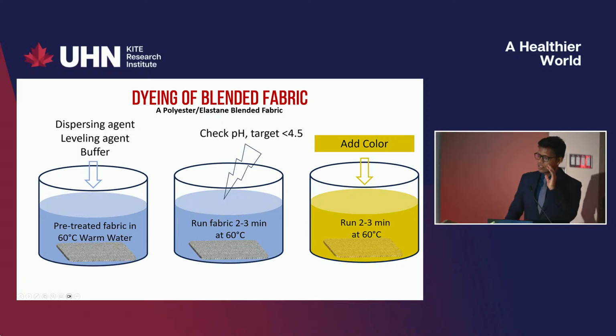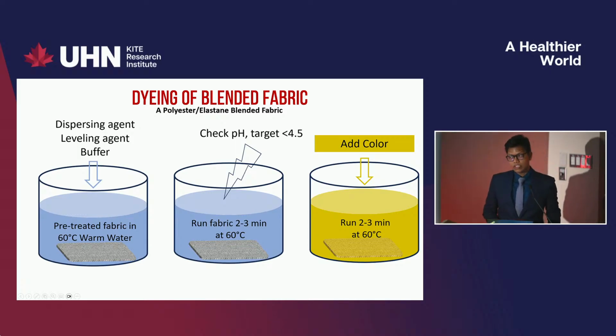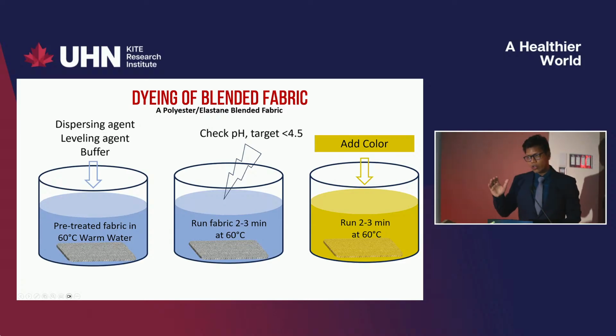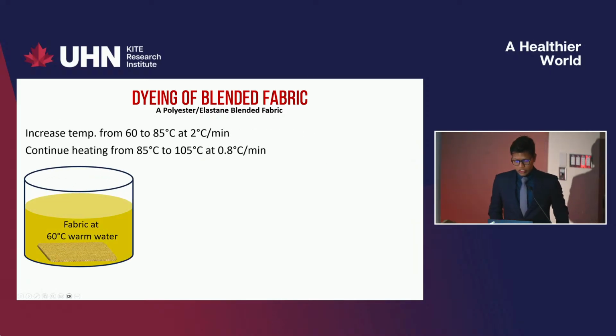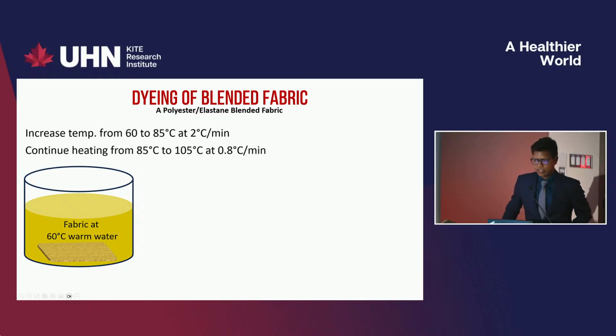So remember, we are dyeing a fabric which is polyester, which is very hydrophobic, and it doesn't bond directly with the dispersed dye. So you are trying to soften the polyester fabric. So you need to go at that glass transition temperature and more than that, actually. But we will do it very slowly so that there is no abrupt stress on the fiber. There is no quick degradation of the fiber. To take that into consideration, we try to start increasing the temperature very slowly. So for this case, I will start increasing temperature from 60 to 85 degrees centigrade at 2 degrees per minute.